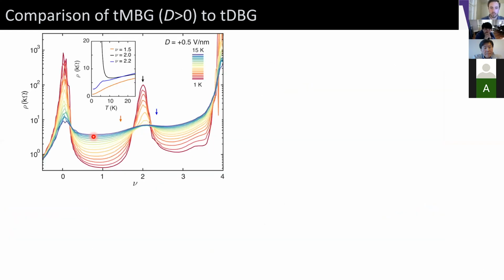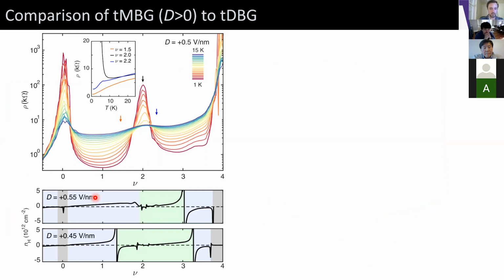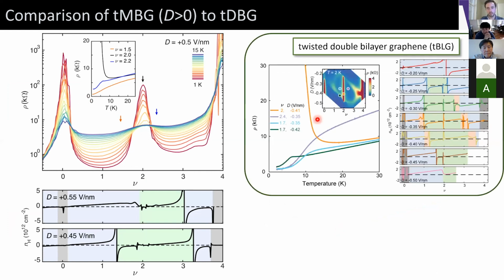And we see that indeed there's an insulating state that develops precisely at half filling as we cool the system down. And then if we look at slight detuning of this correlated insulating state, we see the resistivity has these abrupt drops, indicative of this spontaneous symmetry breaking of the bands. Again, we can also measure the Hall density, and we see that it has extended regions where the Hall coefficient has the wrong sign. And this basically has a one-to-one mapping to twisted double bilayer graphene, where we have these abrupt drops in resistivity neighboring these correlated insulating states. We have these extended regions of the wrong sign of the Hall coefficient.